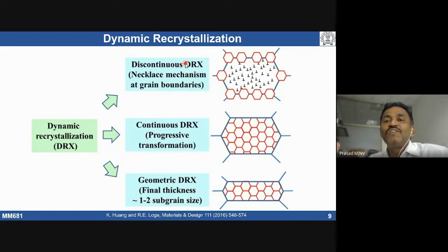Boundaries will have a large energy area. A lot of dislocations get piled up or accumulated around the boundaries. Because of the high energy driving force available, a new grain nucleates at the boundaries, and that leads to discontinuous DRX. So that is the difference. It is not an advantage, it is basically a material property, material behavior itself. Depending on stacking fault energy, we see this kind of difference in the DRX mechanism.